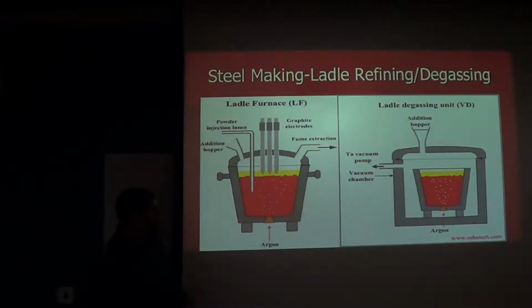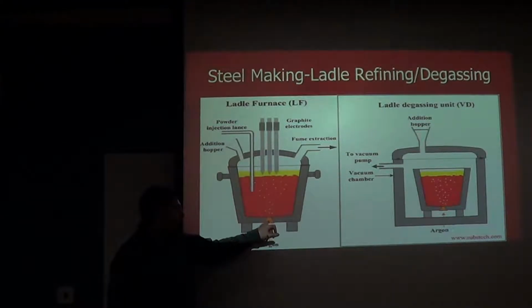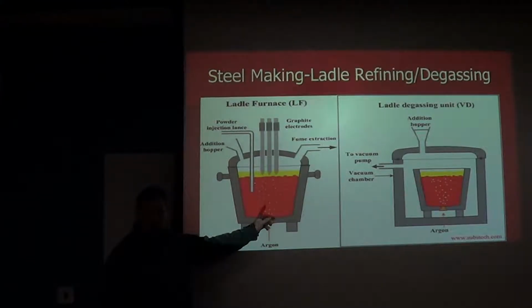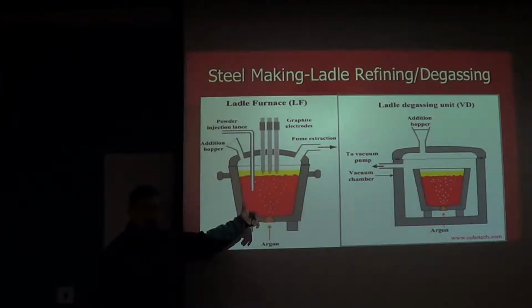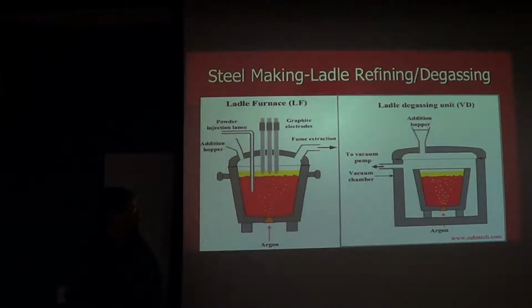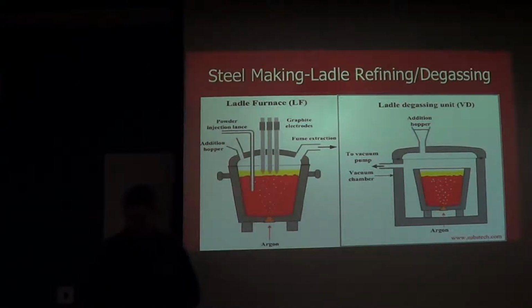And you don't want that little plug in the bottom to fail. So frequently they'll have some sort of a porous plug where they can bubble argon through. That helps with agitation when they're trying to get rid of dissolved gases. One of the mills that we do business with, during their degassing process, can use both argon and induction stirring to really get a lot of agitation going.